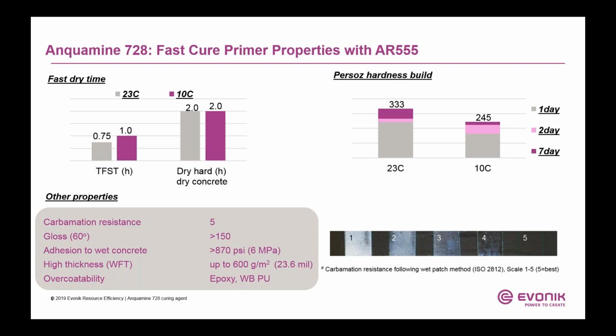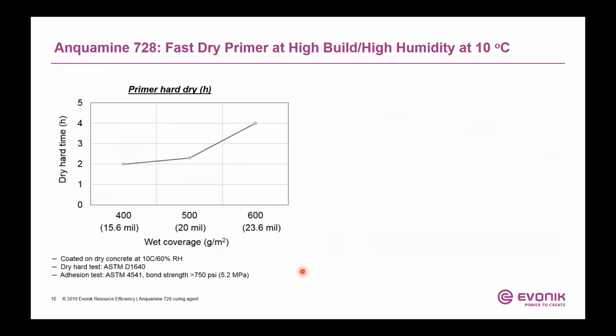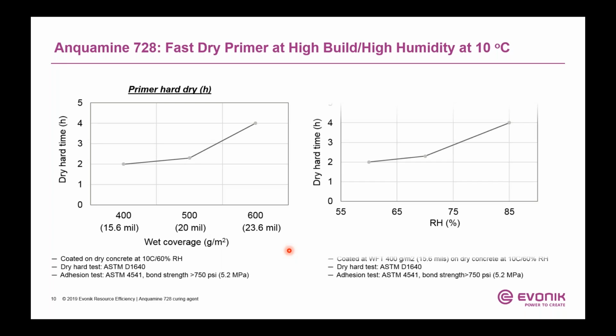We also look into the fast dry speed, like the impact of the coating thickness and humidity on the dry speed. The left-hand side chart shows the thickness varying from about 15 wet mil to 23 wet mil. The dry time lengthens from 2 hours to 4 hours, not too much, and it's still within the critical requirement for a fast dry primer, and these are all done at 10 degrees Celsius. And high humidity doesn't have a huge impact either. Again, it's from 2 hours to 4 hours, even at very high humidities, up to 85% relative humidity.